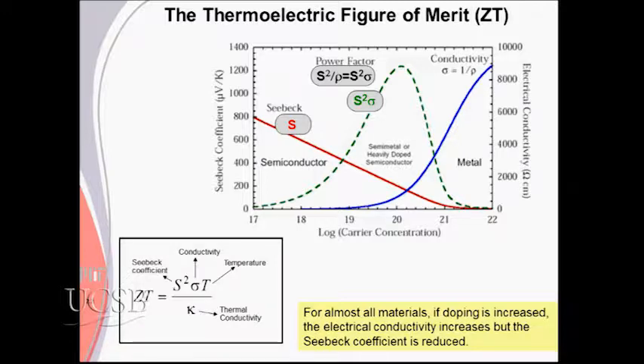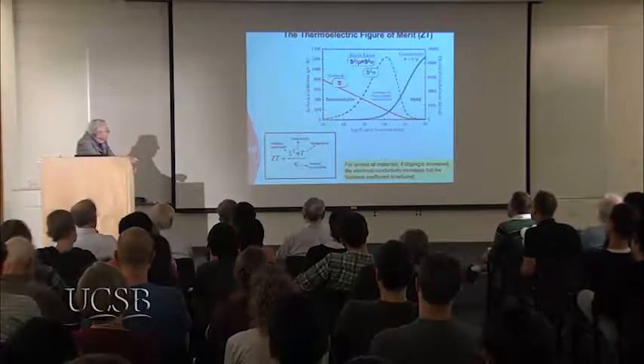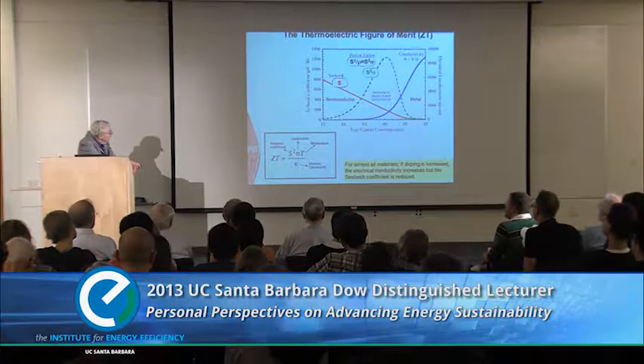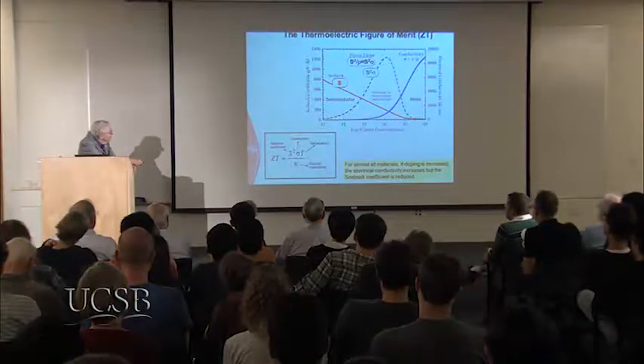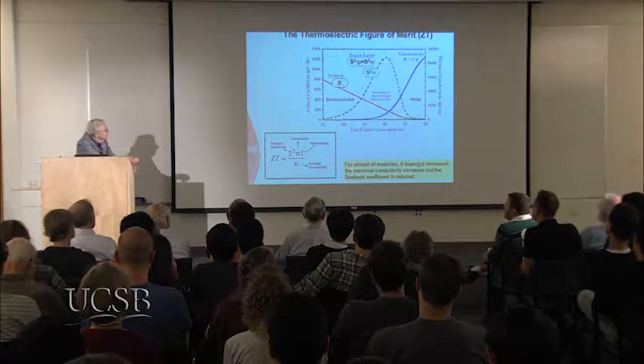At the same time, we want high electrical conductivity. The electrical conductivity is how well the electrons can move without being scattered. So you want them to get from one end to the other without being scattered. And to do that, you need carriers to carry electricity, and so we like a high carrier concentration. So here conductivity goes up. And you see, if you have high Seebeck, you don't have high conductivity. If you have high conductivity, you don't have high Seebeck. So you have a compromise, and this is your compromise.